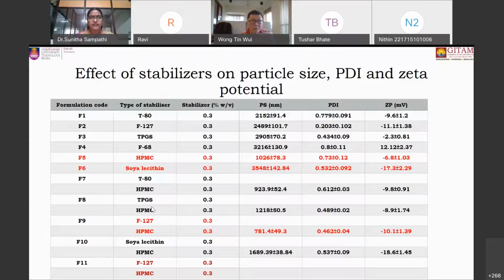We took HPMC further and worked out the combination with various surfactant stabilizers, because a combination of stabilizers always gives us a smaller particle size. The Pluronic F127, which is based on polypropylene glycols, and HPMC resulted in a particle size of 780 nanometers with a PDI of 0.4 and a zeta potential of 10. But we had seen in the preliminary studies that soya lecithin gives a very good zeta potential. So we thought to combine Pluronic, HPMC and soya lecithin at a fixed concentration, and found that it gives a particle size of close to 500 nanometers but with a very good zeta potential.